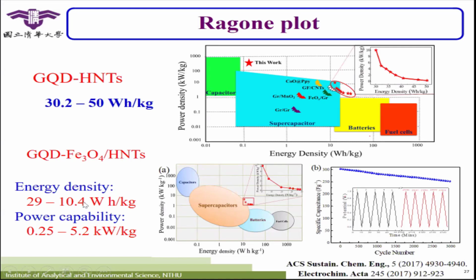The reason is that we count the energy density and power density by weight. For HNT and GQD, they are quite light, so in every kilogram they can have more GQD on the surface, so their power density is high. Since iron oxide is much heavier than GQD, even though their capacitance is high, their energy density decreased a little bit. But no matter whether we add the iron oxide inside or not, their values will be good. For this plot, we call this one the Ragone plot.